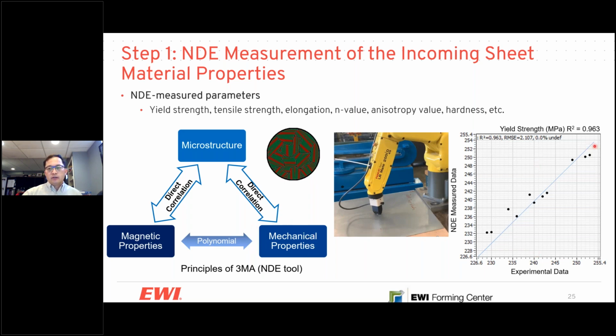The diagram on the right-hand side shows the experimental tensile strength data versus the actual NDE measurement data. This is the yield strength of the specific steel. You can see the correlation between the NDE data and the experimental data is 96%. The yield strength ranges from 230 megapascal up to almost 255 megapascal, a 25 to 30 megapascal variation from coil to coil. That is captured very accurately by the sensor and is very well aligned with the actual tensile test data, which is the experimental data I plotted here together.